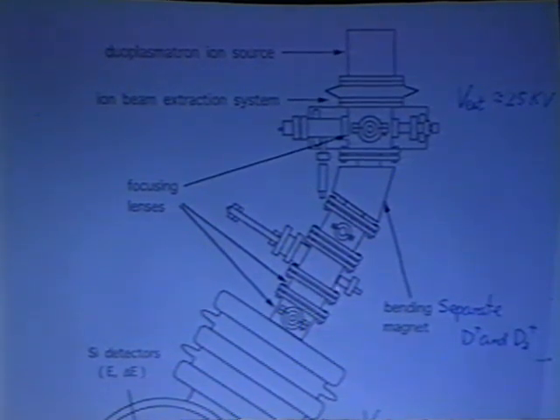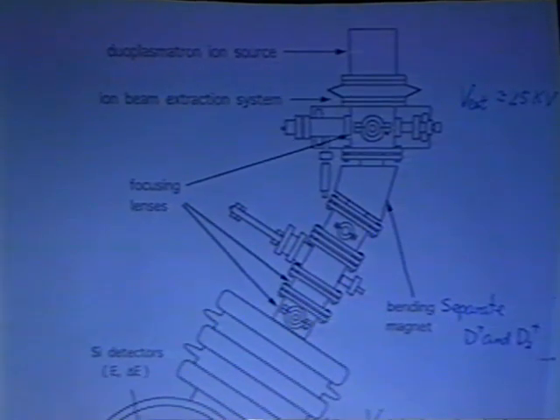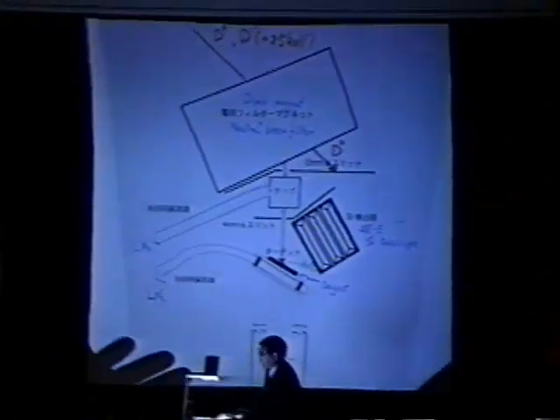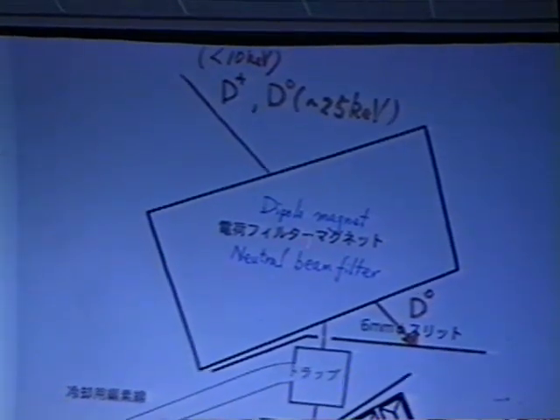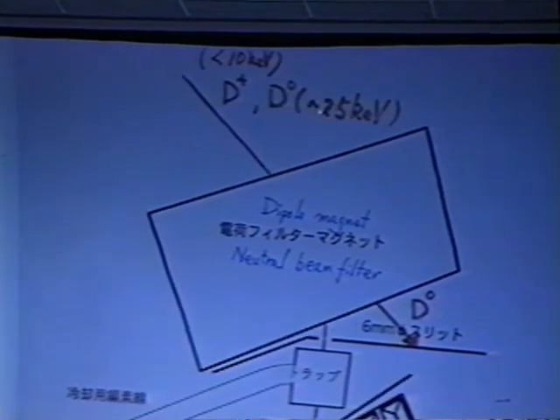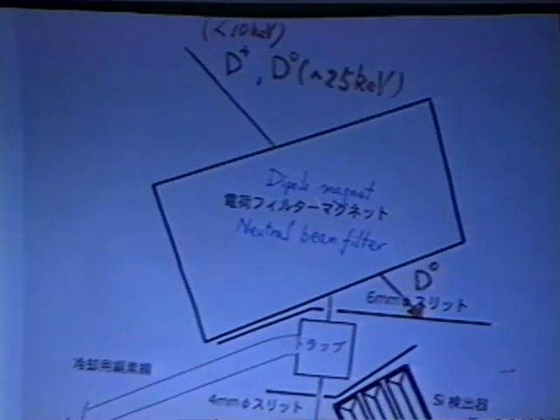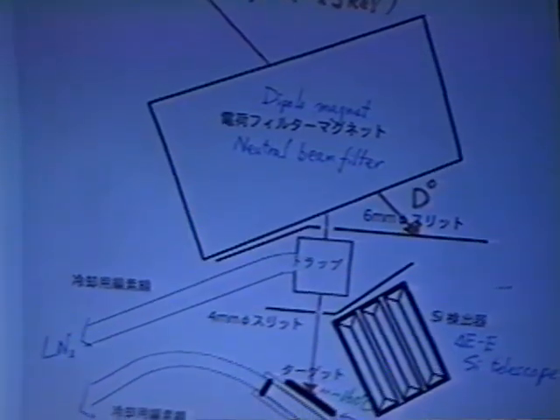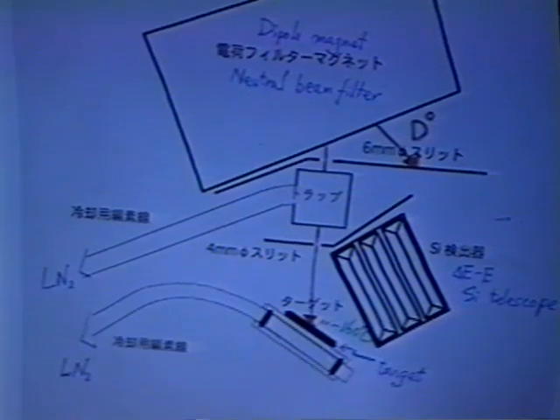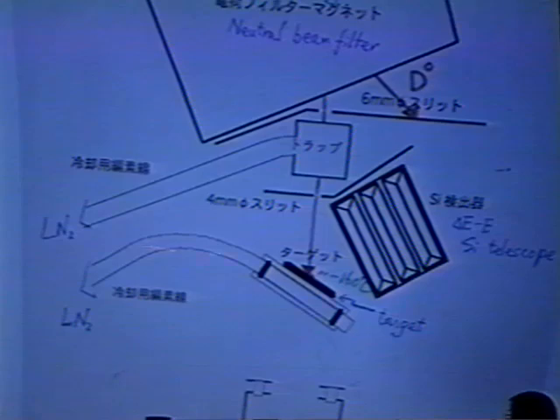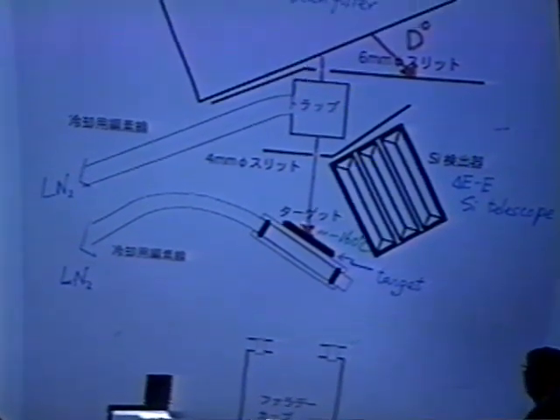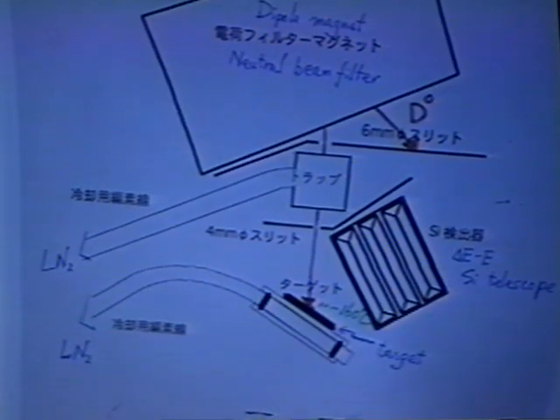But during the transportation, the beam might be neutralized, so we put a magnet just before the target. That's the way we did it. Inside the chamber, the neutral beam goes straight through and has a very high energy, around 25 keV, so we don't worry about it, and only the low-energy beam is bent to the target. In this case, we cooled down the target using liquid nitrogen, and we estimate the temperature at the bombarding spot to be around minus 160 centigrade. We also use our silicon telescope, delta E counter system, just to make sure there is only the proton event.